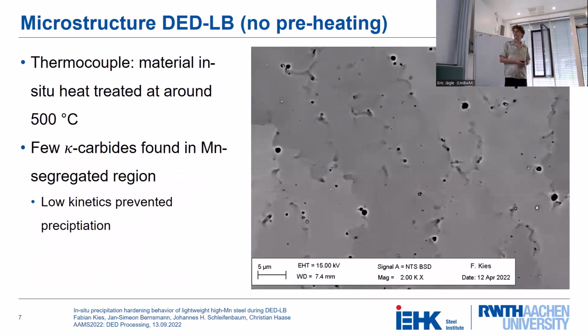So let's take a closer look at the microstructure. First, we're going to take a look at the microstructure without preheating, and the thermocouple told us that the process is taking place at around 500 degrees C, and that's much too low to precipitate κ-carbides during sample manufacturing, just because the kinetics are way too low. And I mean, this is just a normal DED microstructure at this point.